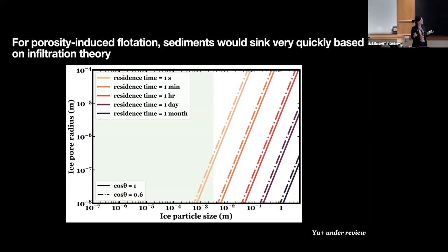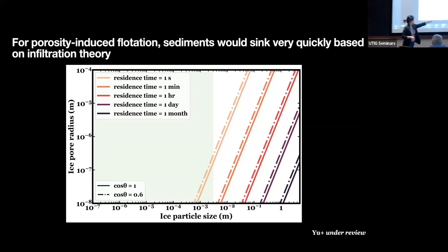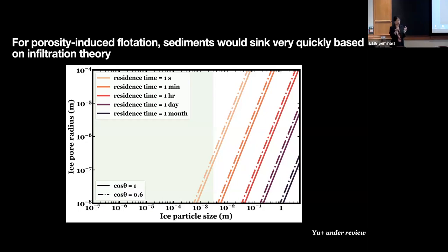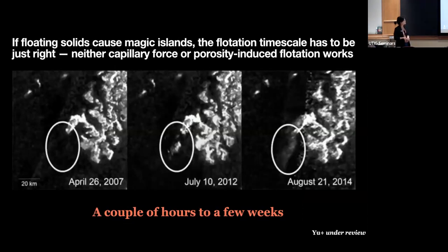Through this infiltration theory we have. And basically what we found is, in order to hit this 1 day, which is the purple line, you have to have very large particles. But for anything that's reasonable sediment size, your flotation time scale is tiny, maybe a few seconds at the maximum, okay? So basically we're like, okay, neither capillary force nor porosity-induced flotation would work, okay?